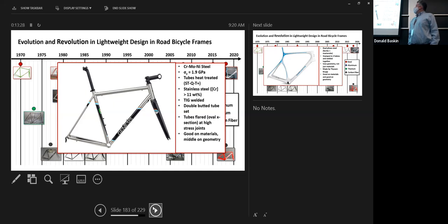Fast forward several years to mid-2010s, so 2015. That's this bike here. This is a huge change in steel technology. This is a stainless maraging steel, also made by Reynolds. It's an alloy of chrome, moly and nickel, and it's a secondary precipitating alloy, kind of like the aluminum I showed you. The way they made the tubes on these bikes is they took a flat sheet, rolled it up, and welded along the line where the two edges met. And I think they heat treat those. So they have to do a solution treat, quench and temper, and then an artificial age.